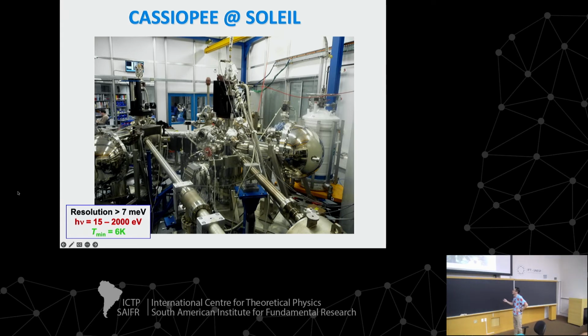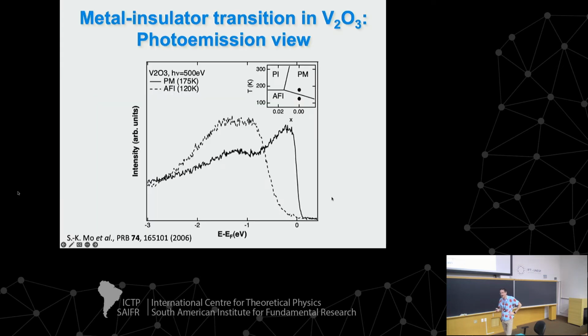V2O3 has actually been measured by angle-integrated photoemission spectroscopy already a long time ago. This is more or less like measuring a partial density of states in the system, and this is what they got. So this is at ambient pressure, zero doping, as a function of temperature. In the metallic paramagnetic state, we have a quasi-particle peak at the Fermi level, and then a bump at about 1 eV below the Fermi level, which is interpreted as the lower Mott-Hubbard band. And then in the insulating state, we have a huge gap of about 500 millielectron volts opening.